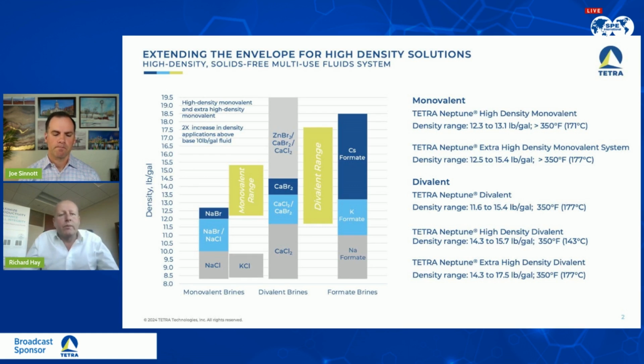So here we achieved this goal by developing monovalent and divalent options. And you can see here, looking at the chart, that in the monovalent applications, we can extend densities from 12.3 to 15.4 ppg for the high density monovalent technologies, with thermal stability up to 350 degrees and sometimes a little bit more. For the divalent applications, which is the larger bar chart on the right there, we cover densities through 11.6 through to 17.5 possible, and that's using either calcium chloride or calcium bromide as a stock brine. And again, we can get thermal stability up to 350 degrees Fahrenheit.